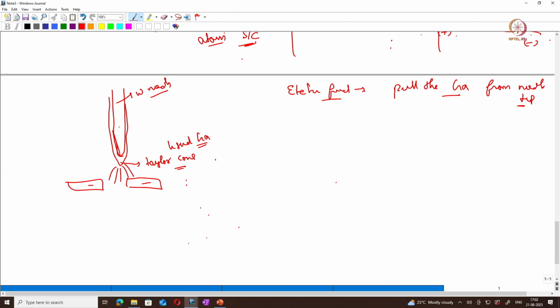But also, due to the presence of the tungsten needle and its surface, there is a certain effect of surface tension. This surface tension can put up a force against the pulling of the gallium ions towards the extractor. Okay, so once the balance is achieved between the surface tension of the gallium and the pulling force of the bias voltage, then the liquid gallium forms a conical shape, which is called a Taylor cone, and that tip radius is between 2 to 10 nanometers or 5 to 10 nanometers.